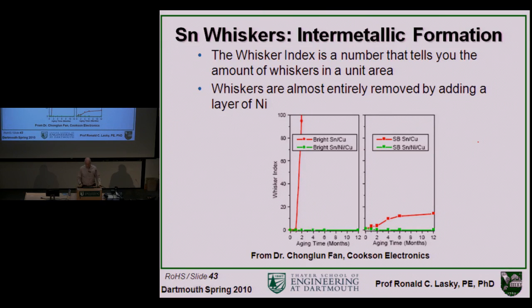This is some work done by my colleague Dr. Fan at Cookson Electronics. And one of the things that people found is if the tin looks bright, you're in trouble because it probably has higher compressive stresses and a smaller grain size. And this is bright tin, and this is the amount of whiskers they got, something they call the Whisker Index. They took bright tin and they put a little nickel at the interface and got essentially nothing. And here they took some bright tin that had a little bit of bismuth in it, and also which reduced it tremendously from here. But when they used the nickel at the interface, it tremendously reduced it.